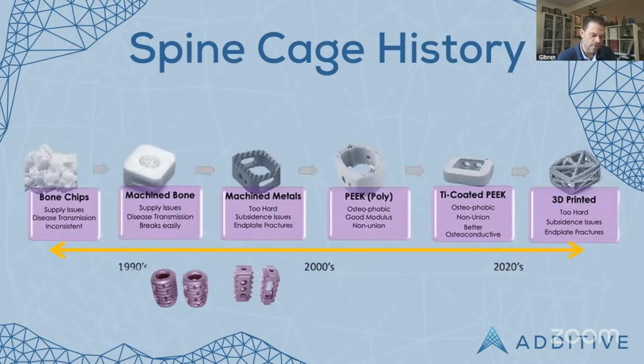It's interesting to have a little bit of a look at the history, right? So this will inform where we've come from and where we're going. Back in the 70s and 80s, allograft was used as a lumbar cage, and they had about 50% success rates. Then cylindrical metal cages were made, developed first for horses and then in humans, and this gave rise to the modern style of interbody cage that we start seeing today. We then moved to PEEK cages, which were really good because they were a lot softer. The modulus of elasticity in a PEEK cage is around 4 GPa, so we were seeing less of the vertebral fractures and less of the subsidence that machined metal cages used to see.